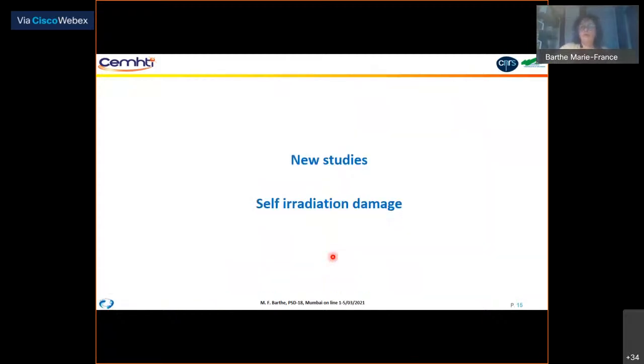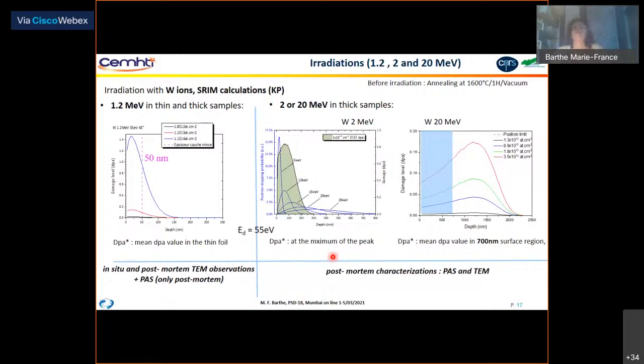So now, if we go to the new results, the self-irradiation damage, we use different irradiation conditions. That means always tungsten ions with energy from 1.2 to 20 MeV. And you can see here the SRIM calculations of the damage profile. Of course, when the energy is low, the damage region is very close to the surface, here within 50 nanometer. If we increase to 2 MeV, it goes to approximately 150 or 200 nanometer.